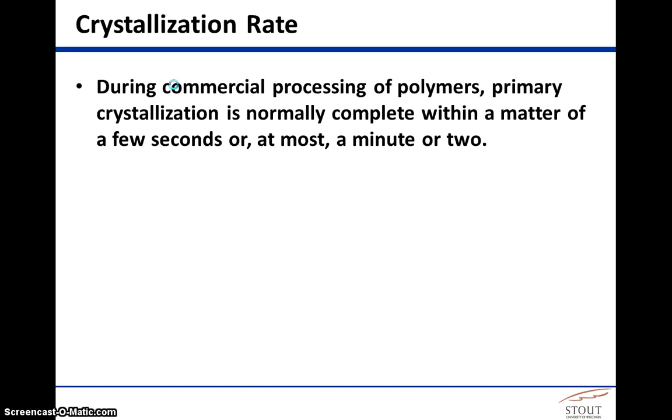If you think about that polymer material that is injected and then held in a mold, you're typically trying to cool that as quickly as you can because you want to cycle through as many parts as you possibly can, but there's a caution there. So if you cool that too quickly, you may not be attaining the full strength of the material because if you're not waiting long enough for the crystals to form.